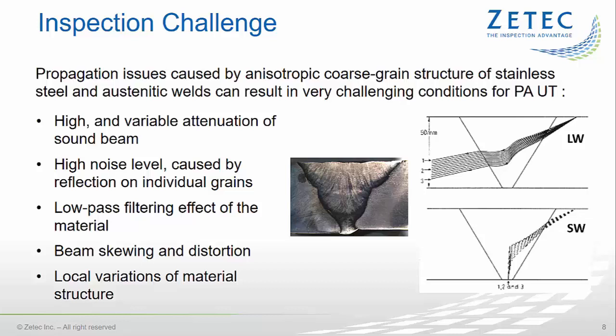Austenitic materials have a much coarser grain structure than carbon steel. Individual grains can be as large as several millimeters. And it is important to mention that this is larger than the wavelength of the acoustic beams that are commonly used in NDT. Also, different grain structures can exist in base material and weld material, depending on the cooling and welding processes. The anisotropic coarse-grained structure of stainless steel and dissimilar metal welds typically results in a strange behavior of the ultrasonic beam when propagating through the material. This finally results in very challenging conditions for phased array UT inspections.